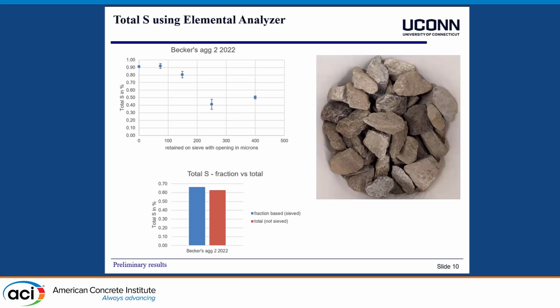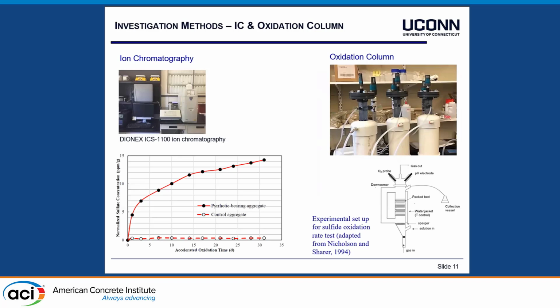The other type of Becker's aggregate we received is this one, where we also crushed it and used the element analyzer with different fractions. Calculating then the average, that's the blue bar there, or you take the aggregate, crush it, and analyze the material as is without fractionating it further, and you see the red bar. And then of course the calculations should match closely to each other. But this type of aggregate, for example, contains about 0.64% of total sulfur.